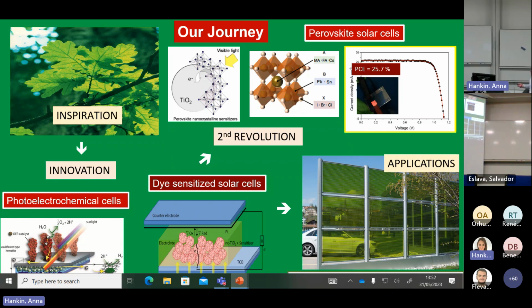However, in these materials, where we use a semiconductor as light absorber, we have minority carriers, and so we have to bring those to the surface to react with water, say, to make hydrogen or oxygen. The issue with, for example, iron oxide is that the diffusion length is much smaller than the light absorption length. So if you use a compact iron oxide, or rust, if you like, and put sunlight on, nothing will happen. However, if you do nanostructuring, you will get currents out of the iron oxide, because now the structuring allows you to capture these carriers. So that was a different concept, but it works to your advantage.